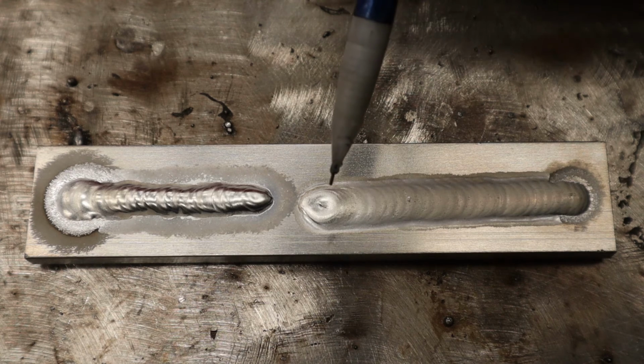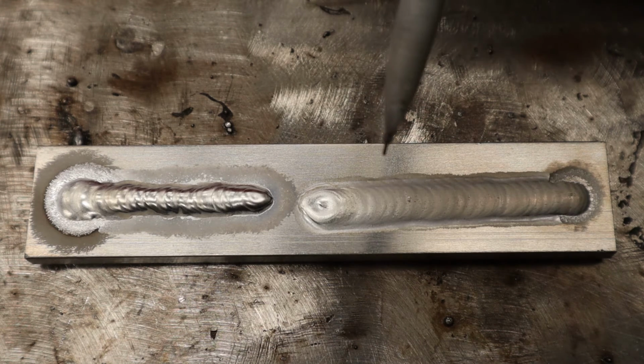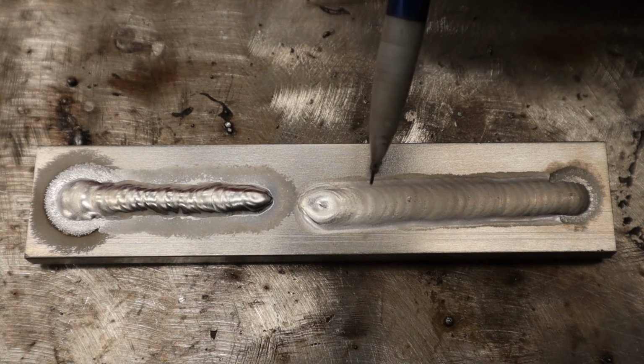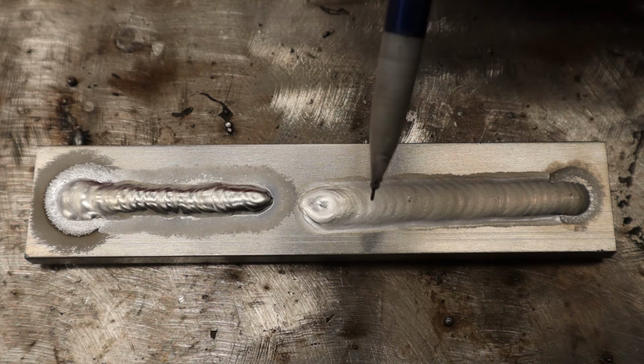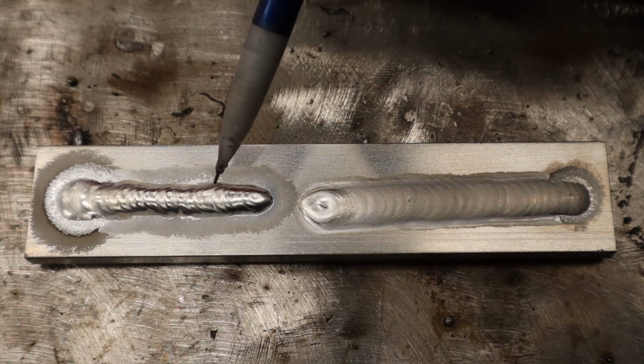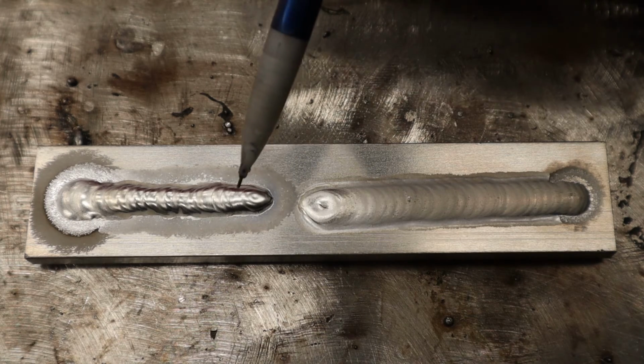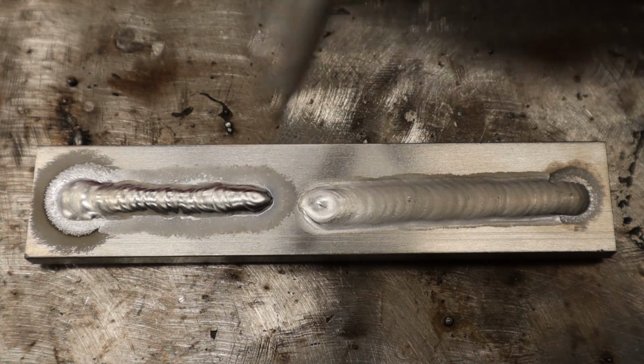Now, that's the other thing to notice here is that with the penetration, we're getting more heat. So that weld bead is a little bit wider, a little bit smoother looking, whereas on the cold side there's less heat, so it's a little bit more colder looking and not as wide.